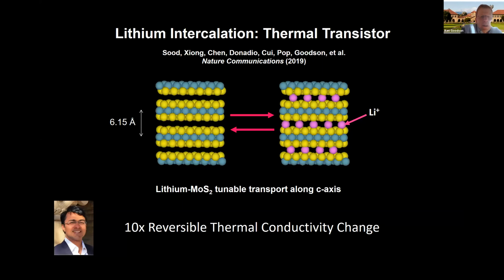In fact, some of the lowest thermal conductivities in dense materials have been reported through stacked monolayers of this type. The interesting thing that we worked on here was to view the material and the stack from the perspective of an energy storage mechanism, and have lithium ions that would intercalate and transport into the stack. This is a mechanism for energy storage that's part of the story around batteries and so forth. We were interested in the impact on heat conduction through the layers and what happens as you bring in the lithium atoms. And what we discovered in the end is that there was a 10 times reversible, fully reversible thermal conductivity change.